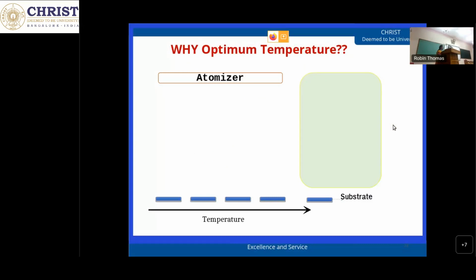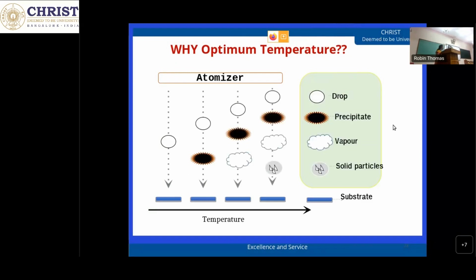Now the question: why do we need an optimum temperature? Each layer will be prepared with a different material, and for each material there will be a particular temperature at which we get a good quality film. Below and above that temperature, the material will have secondary phases which can affect its properties. Suppose the temperature is very low, what will happen? The precursor will fall as a drop onto the substrate, and that will give a very bad film. In the other case, if the temperature is very high, the precursor will vaporize even before it reaches the substrate. Only solid particles will fall on the substrate, and that will also result in a very bad film. So we need to optimize the temperature first.